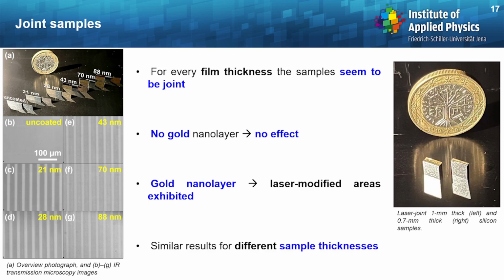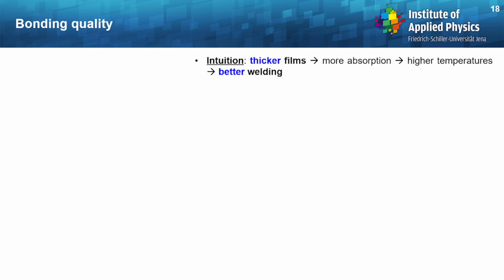We have also tried different sample thicknesses just to ensure that our method is not dependent on the thickness of the samples we would like to weld. And basically it works, as you can see here, for 1 millimeter and 0.7 millimeter thick samples. Okay, now concerning the bonding quality.